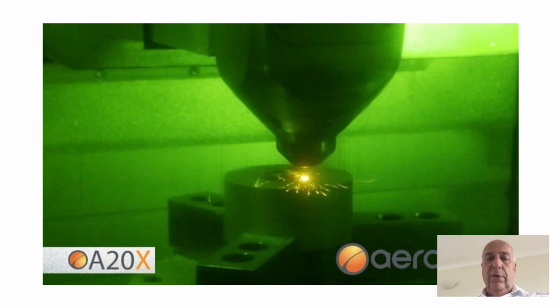The picture on the top right hand corner is a very small piece of work we've done in the project, but we're very keen to show it, as all of the other results are on laser bed sintering systems. There is a need to be able to use what we call the coarse powder that's atomized, and in this instance this is an example of a laser fed blown powder system which could eventually use the higher size particles that come from atomizing. This can make the economics very much better.